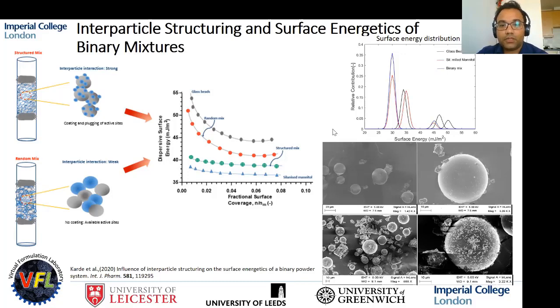Now, further to this, we also deconvoluted this IGC experimental data using a computational model based on Boltzmann probability distribution to get a quantitative estimation of the distribution of energetic sites for these components. So on the top right-hand corner, you see distribution of different energetic sites for glass beads, binary mixture, as well as the silanized mannitol components. And we see that for the binary mixture, the energetic sites have moved to the left toward the low energy component in case of structured binary system. This was also confirmed using SEM images. So the top two images show a case of random mixture where there's no coating, whereas at the bottom we see coating of glass bead particles with mannitol particles. So to conclude, next please.